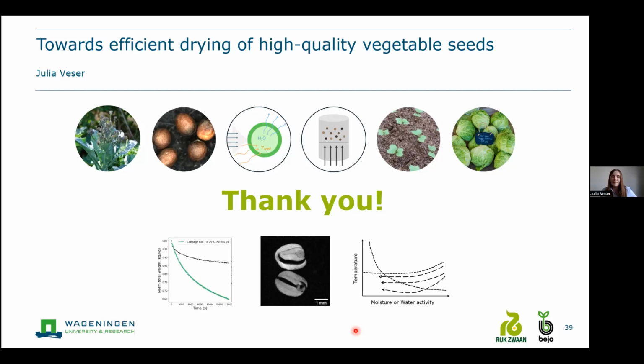Yeah, definitely. In this case, we see one extreme drying, with quite low relative humidity of the drying air, so basically a high driving force, nearly 0% or like 4% relative humidity. That's quite a harsh drying, I would say. Therefore, we have these quite big gaps. Until now, we couldn't evaluate more drying pathways in the MRI, but I assume that if we do that with a higher relative humidity, perhaps a bit longer, then we won't have these big cracks. So I definitely think that we can vary that with different conditions.